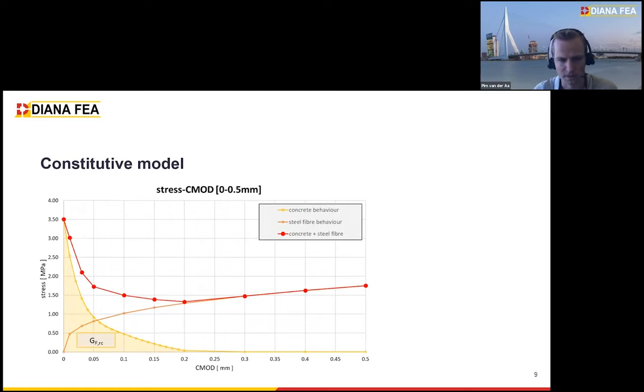What we did next is summarize the softening behavior of the concrete, which is in this diagram included in yellow. That's a Hordijk softening curve you see. With the orange line, it's similar to the hooked end fiber you just saw, so maybe it follows some sort of root function. It goes up to 1.5 in this diagram, but you can already see that between 0.1 millimeter and 0.3 millimeter, there's a small dip or drop.